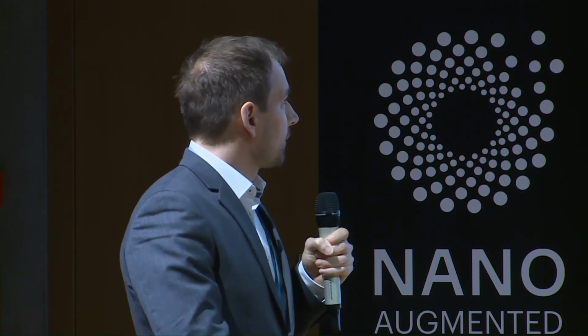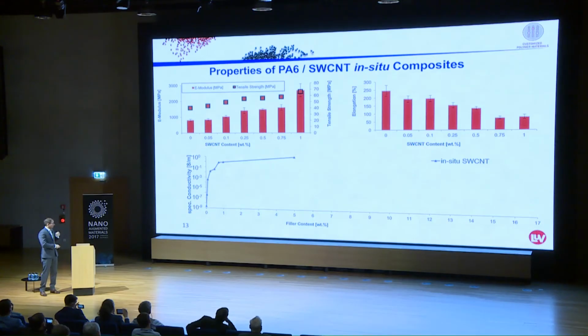What we see here is the filler content against the specific conductivity. Even with 0.05 weight percentage TUBALLs, we have a significant increase of electrical conductivity, and the percolation threshold is crossed at about 0.1 to 0.2%. So this is pretty nice.